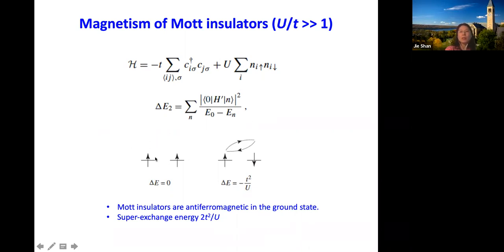In this case, this is forbidden, but in this case, you can work out that this state has a lower energy, and it's lower by T squared over U. So from this simple perturbation theory analysis, we also know Mott insulators are antiferromagnetic in the ground state, and the super exchange energy is on the order of T squared over U.